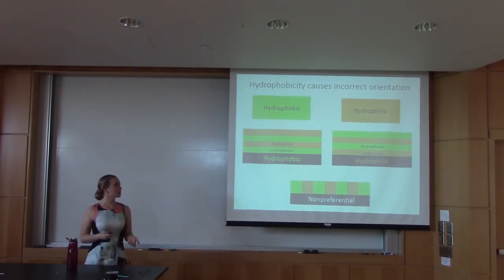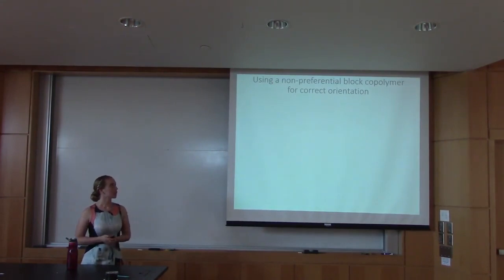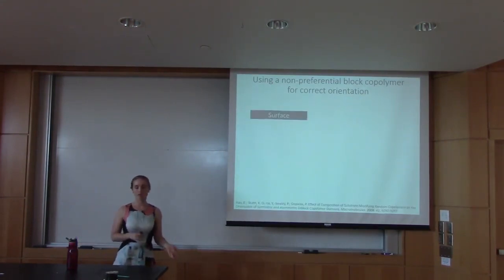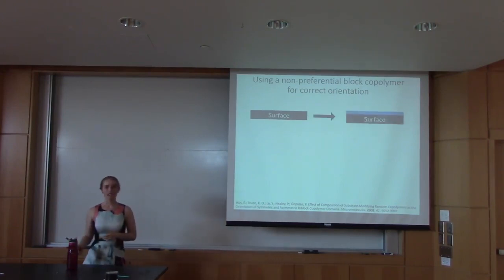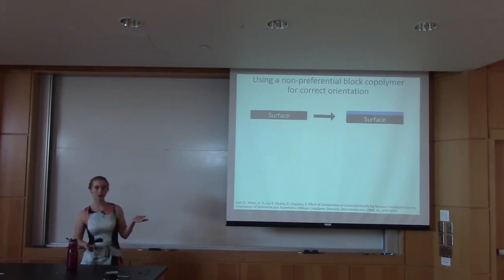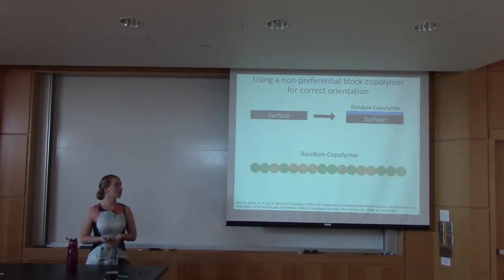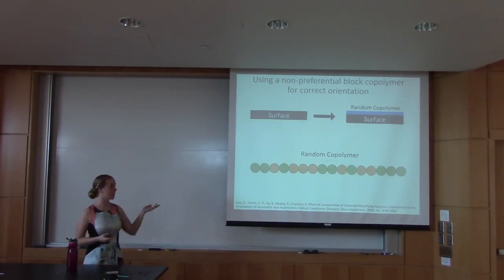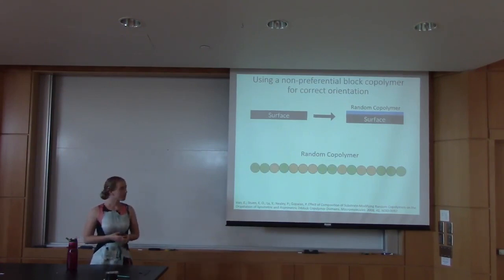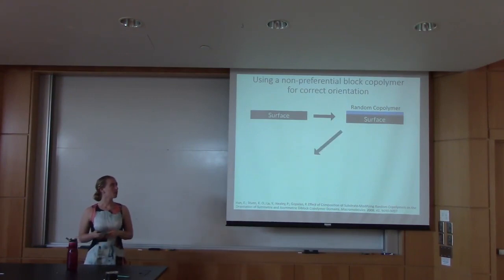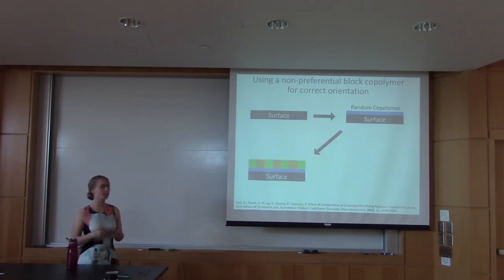And the way that we propose doing this is through a similar method to before, where we start with our surface, and then instead of immediately adding on our block copolymer, we add on this blue strip. Now this blue strip represents our random copolymer, which if you'll recall is this unordered, unorganized way of having the formation of this polymer. From there, we add on our block copolymer and hope for a perpendicular orientation of the block copolymer relative to the surface.